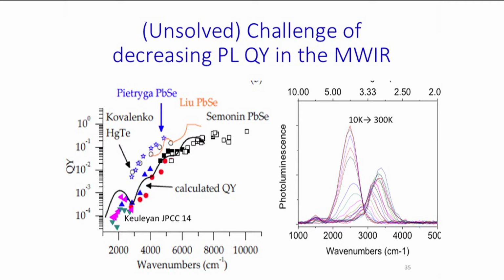It's important that we improve it, because if we don't, we will always be limited in terms of the maximum efficiencies of those detectors. We want to have as high a quantum yield as possible to have the best possible detectors. So we're down there when we go into the long wave infrared. It seems to saturate afterwards, but it gets pretty low quantum efficiency. Why is there such a low quantum efficiency?